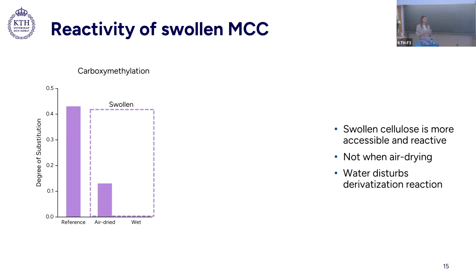So I did my swelling, I got this amazing highly swollen material, and then I tried to do some carboxymethylation. And as you can see here, it did not work. So on the wet material, the carboxymethylation reaction is an ether reaction, so it did not work together with water. And then when we dry it, we see the hornification effects. So it was not even as reactive as the reference, so it's better to just do nothing.